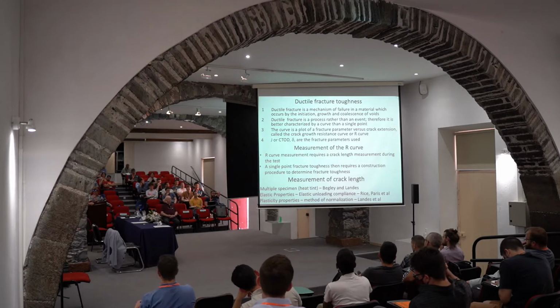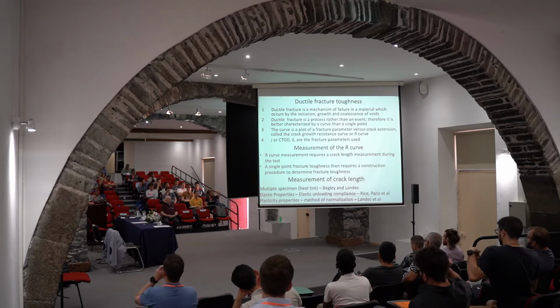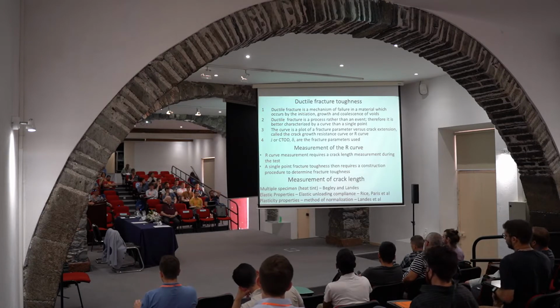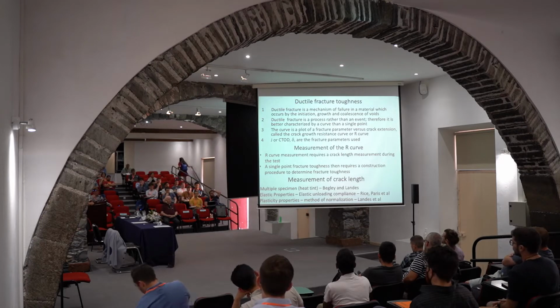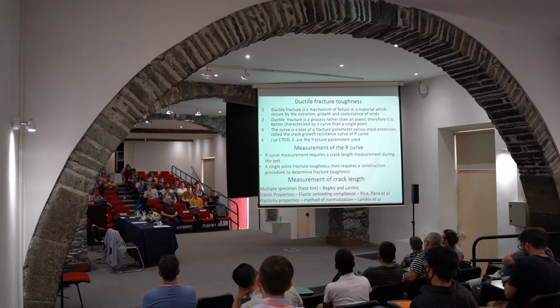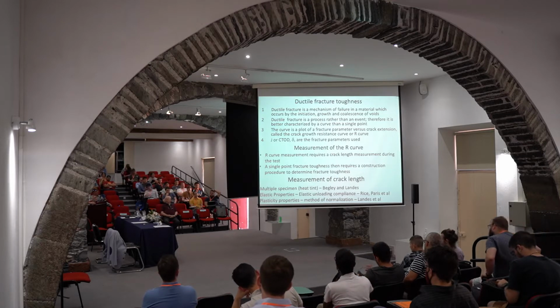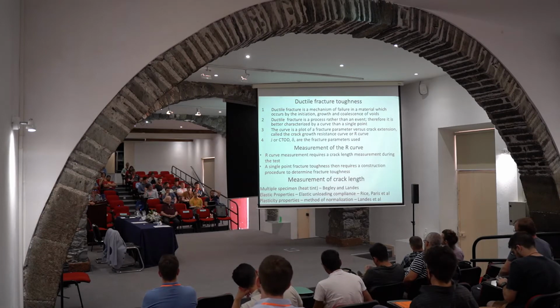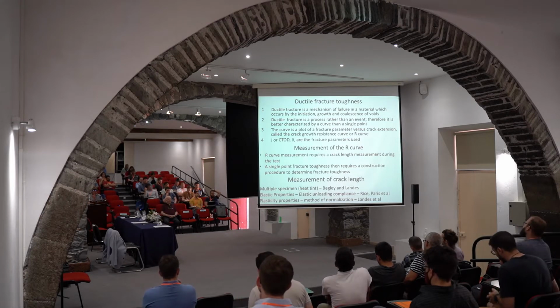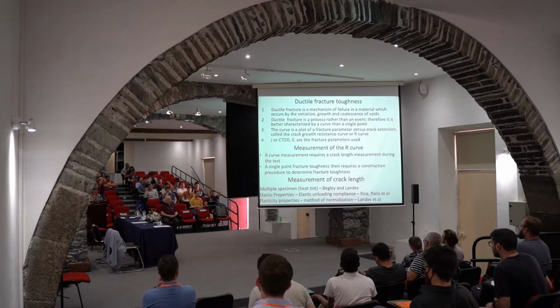And just to emphasize, Begley and Landes' first efforts were the so-called multi-specimen technique, which means that they needed at least 4 specimens to get this curve. But later on, also due to research of Rice, Paris, which is another fracture mechanics legend, and their co-workers, the single specimen technique was introduced, which is nowadays exclusively used.